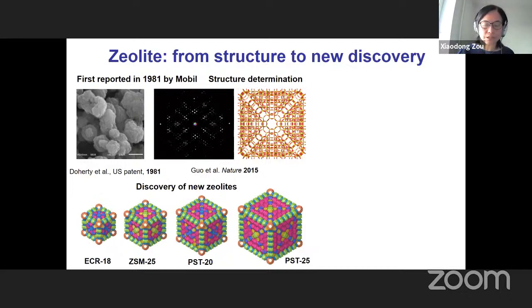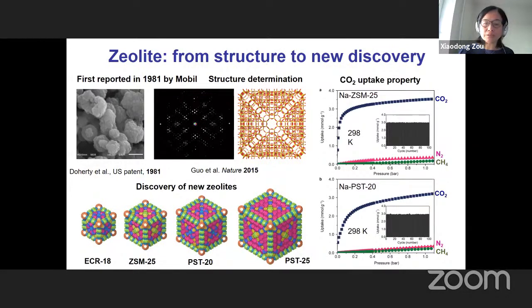If you look at the different colors of these building units, they correspond to different cages, and they are built from the exact same building units in all these zeolites. And we discovered a series of zeolites, and you can see here they have very, very good CO2 uptake properties. The reason is that the ring size of this zeolite is similar to CO2 and nitrogen, so the nitrogen is too large to enter, but the CO2 enters perfectly, so you have very fast and very high CO2 uptake, but exclude nitrogen gas and also methane in this case. It can also be cycled many times, very stable. So this is a very promising CO2 absorbent.